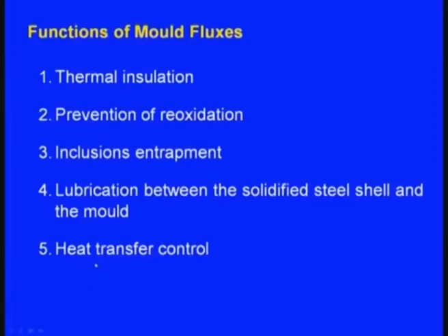If this lubrication is not there, the solidified shell will stick to the mold wall and will break as it is pushed downwards. Fortunately, these mold fluxes act as lubricants. Next one, they also control the heat transfer rate, so that the shell will solidify at the required place and at the required time.